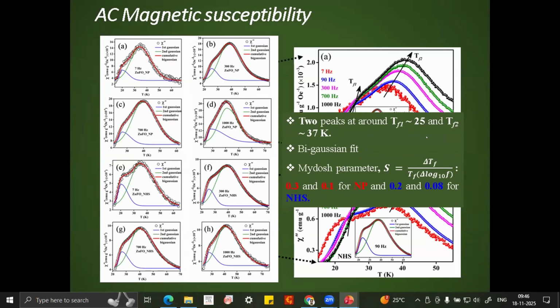Now, once we have the peak position, we can estimate the Mydosh parameter from them. So now this Mydosh parameter is 0.3 for nanoparticle for the lower temperature curve. On the other hand, the same Mydosh parameter is around 0.08 for nanohollowsphere for the higher temperature curve. Now, this is a second indication that the nanoparticles can be dominantly of superparamagnetic nature. On the other hand, the nanohollowspheres can be of spin glass nature. But this is also not a conclusive evidence.